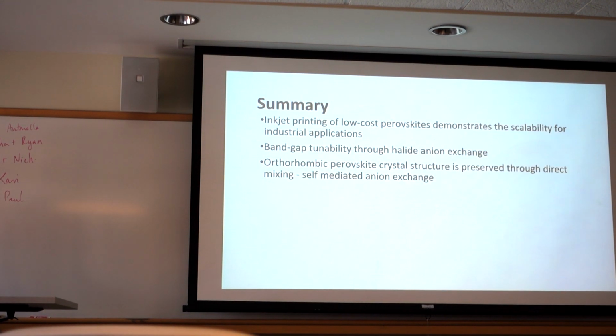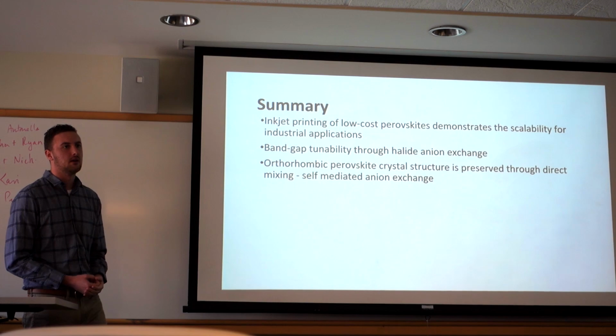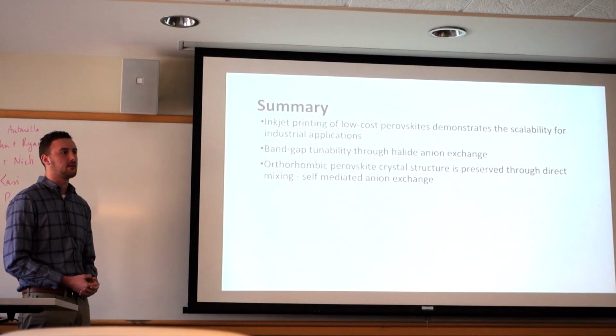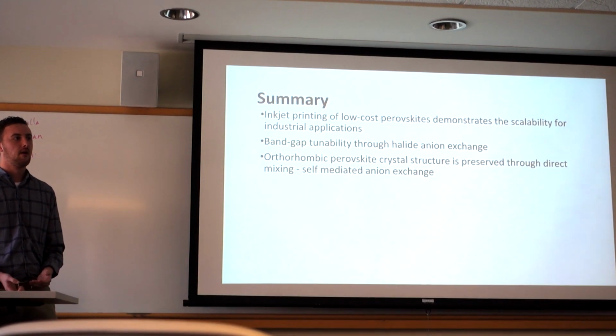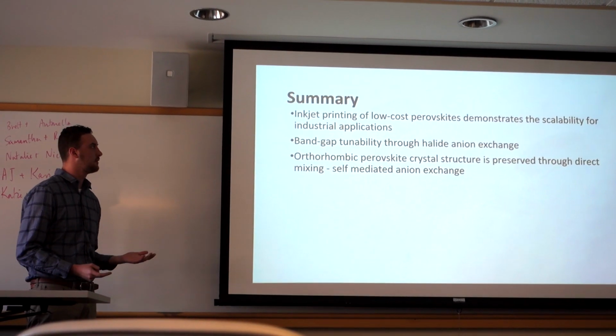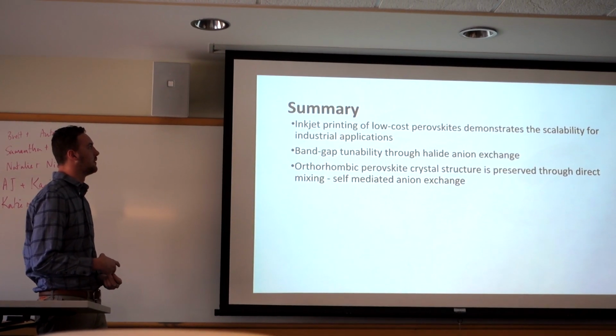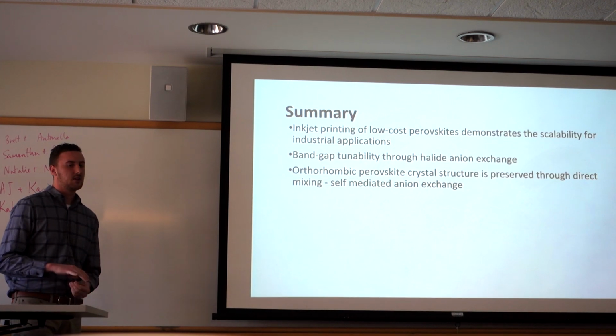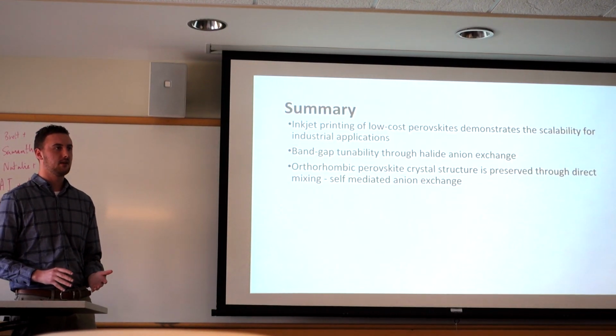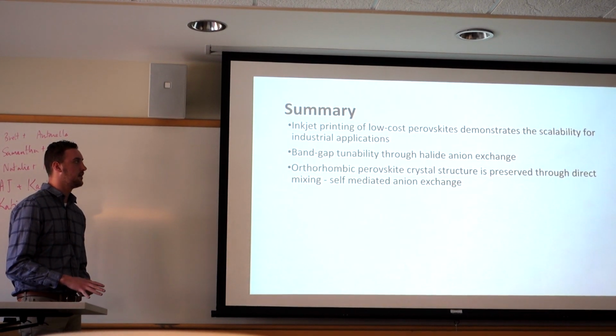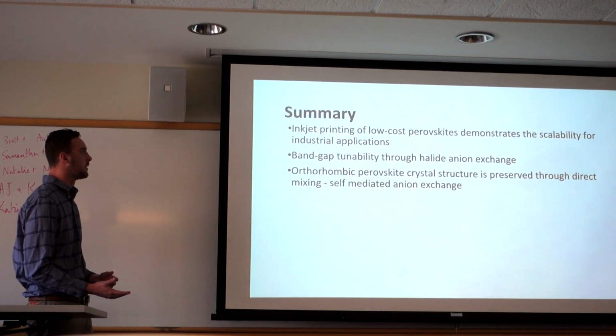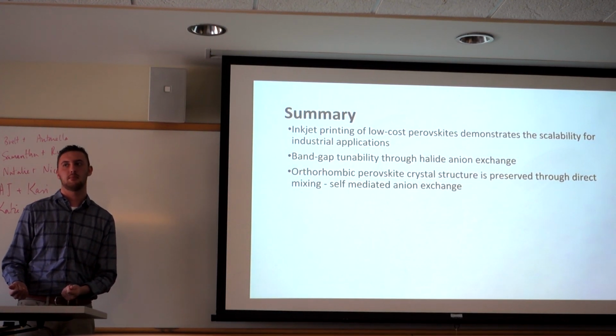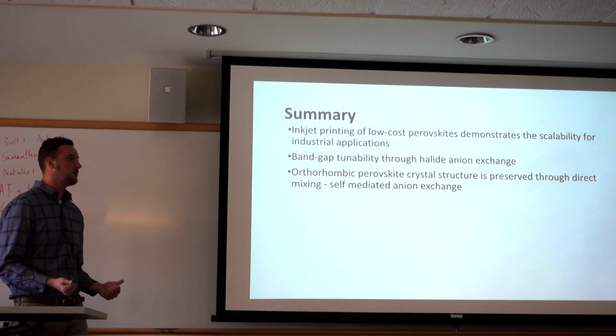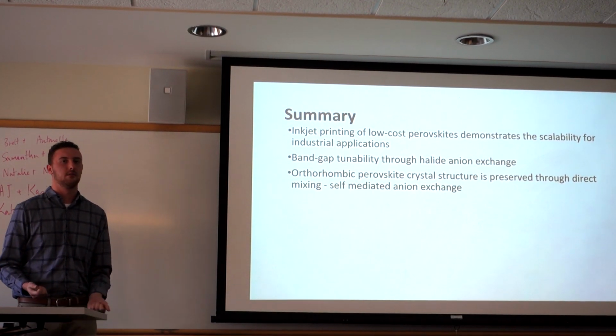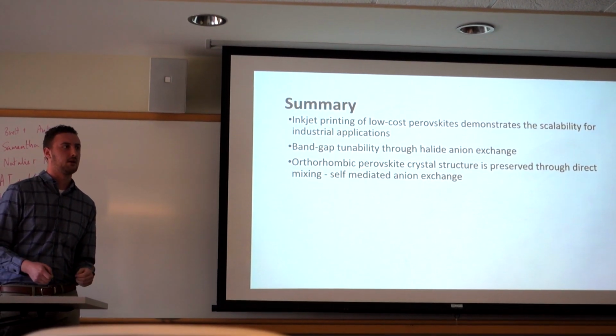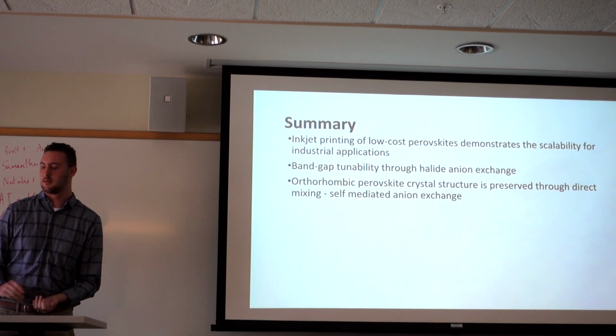So in the future, we hope to take transport measurements of our material. The Nebraska group was very successful alone with cesium bromide. We were having troubles with our mixed films this past summer. So in summary, the inkjet printing of our perovskites demonstrates a novel prototyping method for industrial use and its scalability. We were able to fine-tune our band gap through halide exchange, and we were able to preserve the crystal structure of our perovskites through direct mixing and through alloy. Thank you.